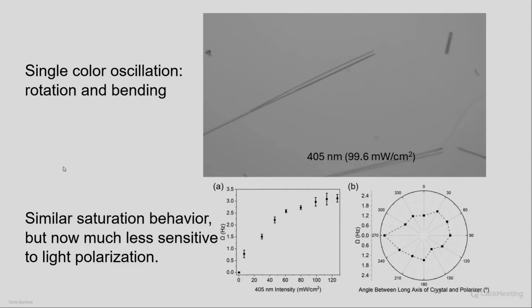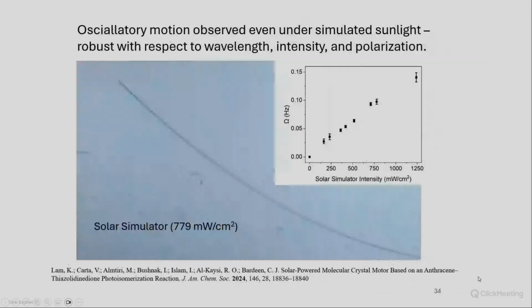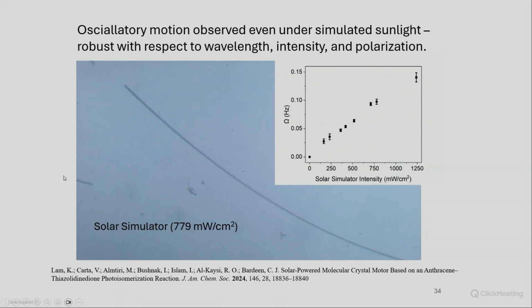You get the same saturation behavior. The dipole allowed nature, the polar plot's not quite as good. We think we understand that. But then the last part is these guys are very robust oscillators. So this is under solar irradiation, so a higher intensity solar simulator. But this is broadband irradiation, and also you get this sort of oscillatory motion, in this case bending. It's trying to twirl, but it looks like a bend.